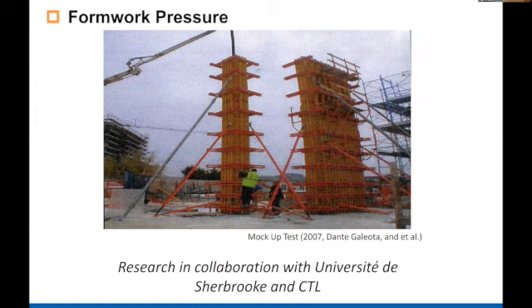self-compacting concrete is that when you pump concrete like water, and the concrete reaches the top and it's still water, then the hydrostatic pressure at the bottom could be like water. And that means that formwork design has to be changed, because in conventional vibrated concrete, you'd be slow enough so that the pressure at the bottom is less than hydrostatic. So can we have concrete which flows like water, but still has lower hydrostatic formwork pressure? And I will show you that you can do it by addition of nanoclay.